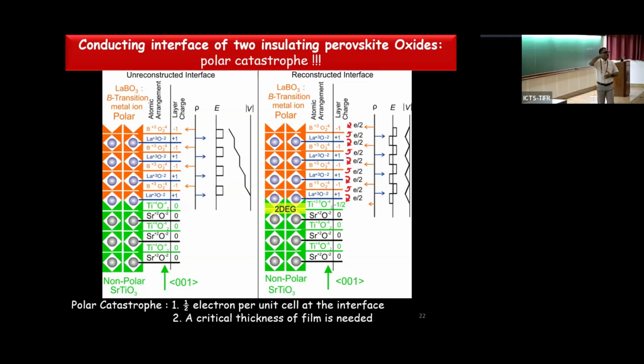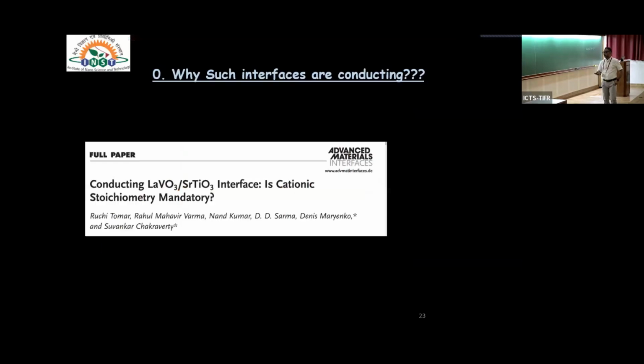As you start growing the material thicker and thicker, this potential starts diverging, and nature doesn't like this diverging potential. What it does, people believe, is send half of an electron from the top surface to the interface. This gives rise to a non-diverging potential, and people believe this is the origin of what is known as the polar catastrophe scenario. So what will be the signature of that? The system should be half electron doped per unit cell, and a critical thickness of the film is required to get this interface conducting.